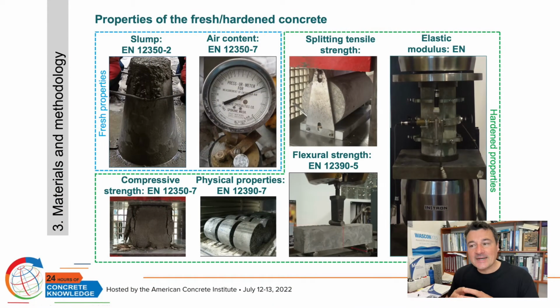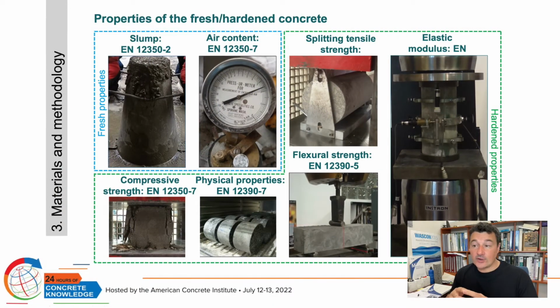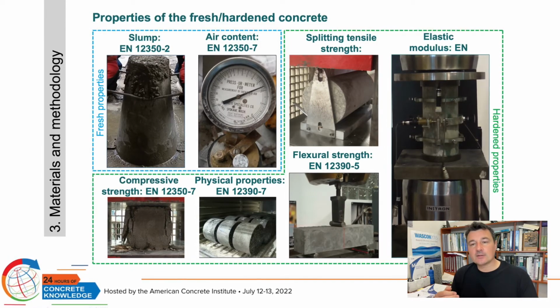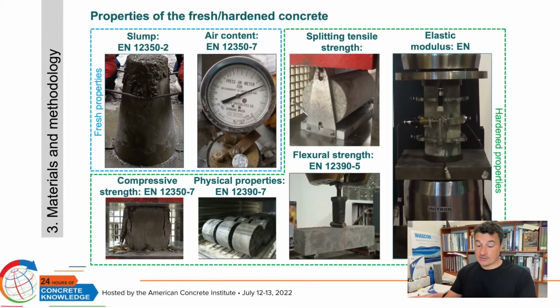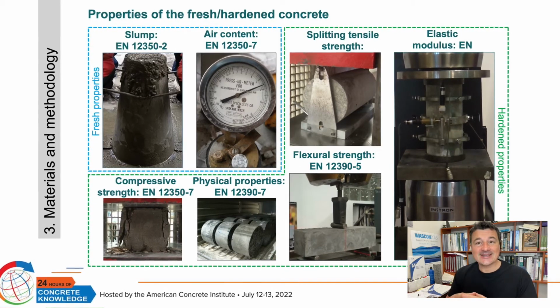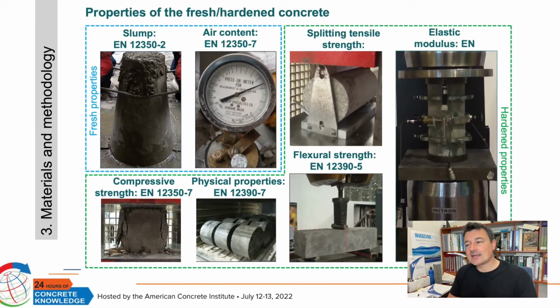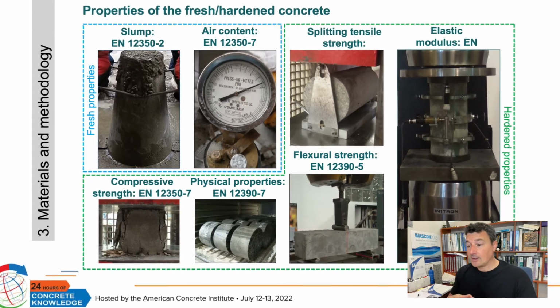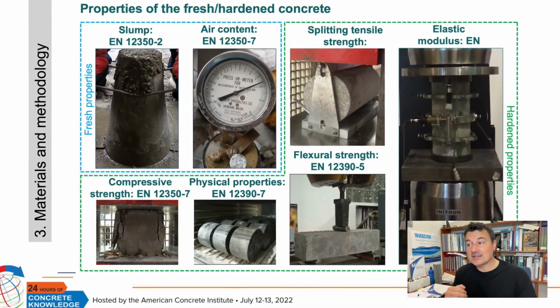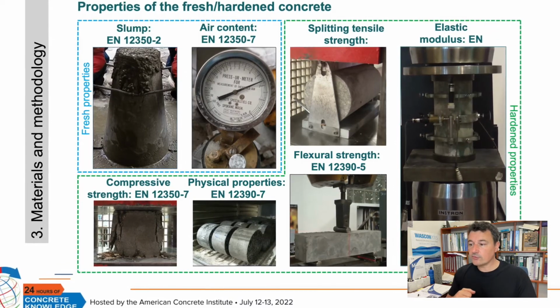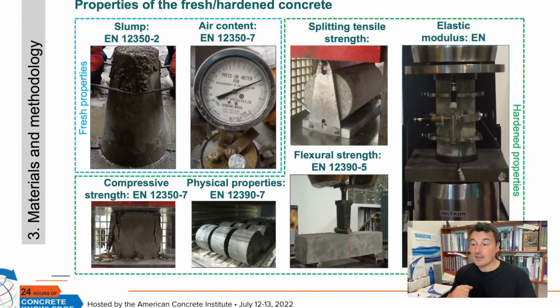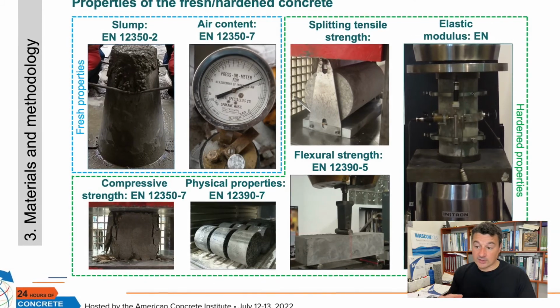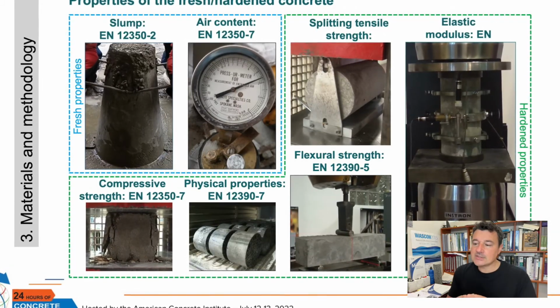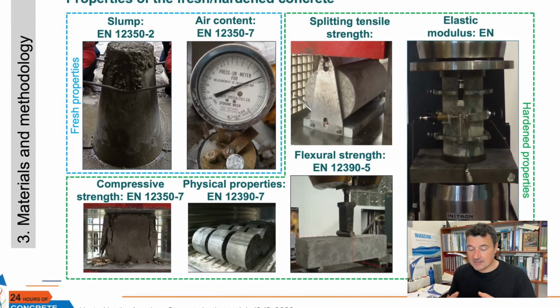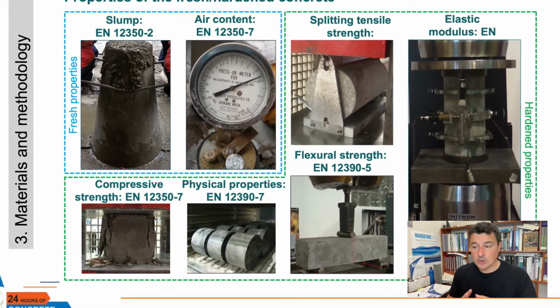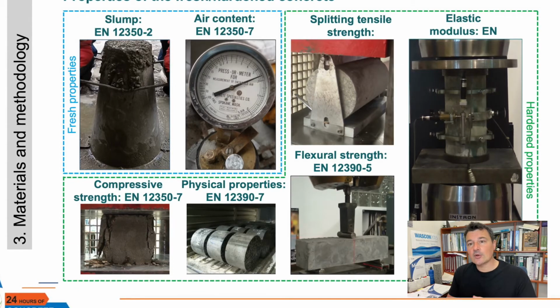What about the properties of the fresh and hardened concrete? First, for the fresh concrete, we determine the workability using the Abrams cone for determining the slump. Also, the air content of the material was determined. For the hardened concrete, the splitting tensile test, elastic modulus, of course flexural strength of the material, the compressive strength of the concrete, in this case using cubic samples, and also the physical properties, the density, the porosity, and the absorption of the siderurgical aggregate concrete.